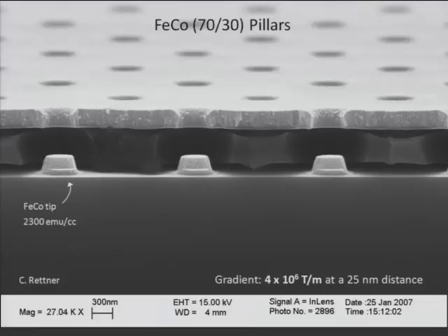But if you make some magnetic calculations and you assume sort of the ideal magnetization inside here, the calculations say that you should have about 10 times higher gradients than you actually measure. So there is still quite some work to be done here in understanding how to make very small magnets that are producing very, very strong gradients. But this is essentially the state of the art at the moment.